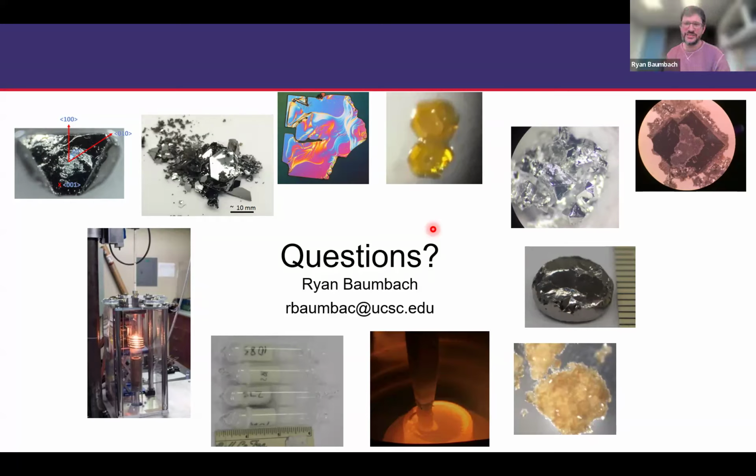Okay. Very difficult. Boron is a giant pain, but a few recommendations. One is that aluminum is kind of a go-to flux. You can't get a lot of boron into aluminum, but if you make the ratio mostly aluminum, 100 aluminum to 1 boron, then you can do that. And that's something people have done for hexaborides and dodecaborides for a long time.